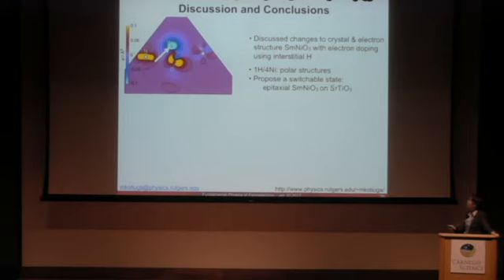So I'd like to come to my conclusions. I've discussed how we can change the structure of SNO using added hydrogen, which causes electron doping, and the electrons actually localize on one nickel and are not itinerant in our structure. We've studied just one hydrogen added into a 4-nickel unit cell, and this gives us a polar structure, and we can have a switchable state with samarium nickelate with this intercalated hydrogen constrained in a cubic in-plane situation, constrained to the lattice parameter of STO.